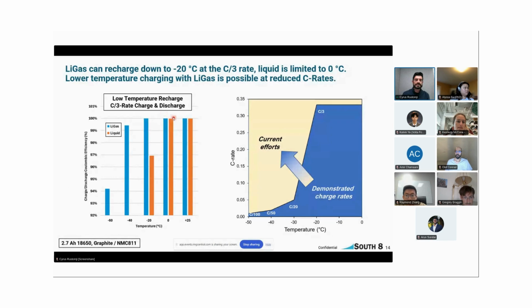At 0 degrees Celsius, you can see liquid and LiGas perform similarly well, about 99.9% Coulombic efficiency during charging and discharging at the C/3 rate. When you get to minus 20, you see a pretty considerable drop for your liquid electrolytes. That's really due to all the lithium plating that's starting on your anode, which decomposes your electrolyte and kills your cell pretty quickly. Yet LiGas still maintains very high Coulombic efficiency at minus 20 at the C/3 charge rate.